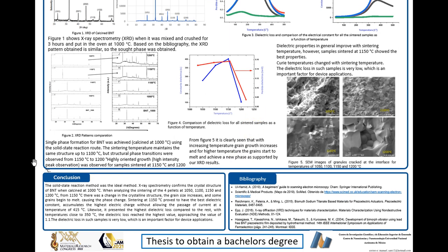So in conclusion, we can say that the solid state reaction method was the ideal method. X-ray spectrometry confirms the crystal structure of BNT when it's calcinated at 1000 degrees. When analyzing the sintering of the 4 pellets at 1050, 1100, 1150, and 1200 degrees, from 1150 there was a change in the crystalline structure. The grain size increases and some grains begin to melt, causing the phase change, as we can see from the XRD pattern here and from the images.